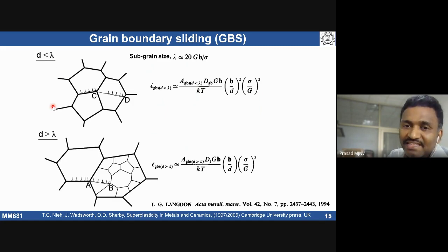Based on grain size, whatever I mentioned, the previous two mechanisms are two different types of grain boundary sliding. Now the shape change: how does it come about? If there is diffusion creep, then we do see elongated grains. If there is not much shape change, that means the dislocation climb mechanism is accommodating the grain boundary sliding. That's it, that ends there.